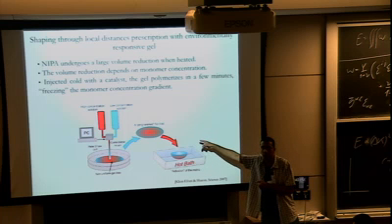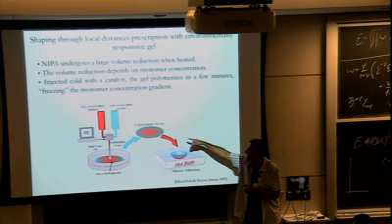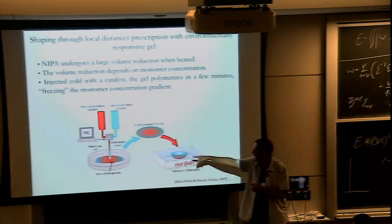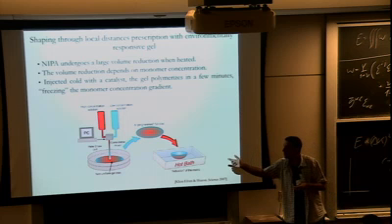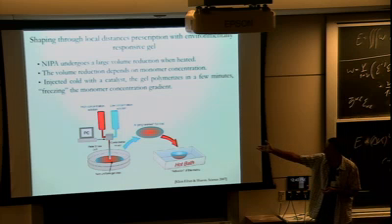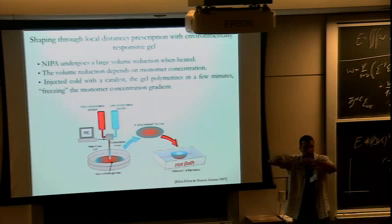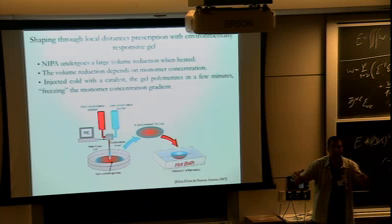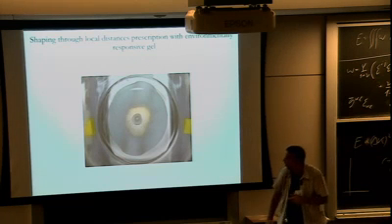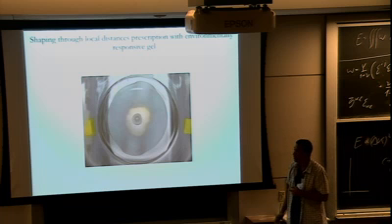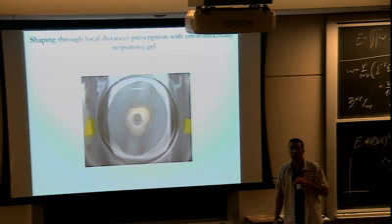In the most dilute regions, it's going to shrink a lot. So when I take this thing and I shrink it up, I can have a different metric. Only axisymmetric metrics in this setting, but for this case, I can have a dome-like metric. It's going to be a positively curved metric.